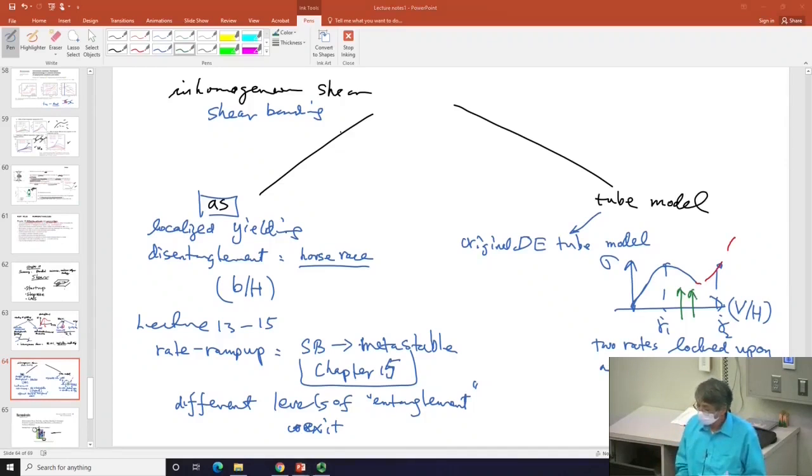In this scenario, you can see there's no time here. This is in steady state. So this scenario says you must have shear banding. But this rate run experiment showed you can avoid shear banding if you avoid this sharp startup. In fact, even though it's difficult to avoid, it turns out you can avoid.